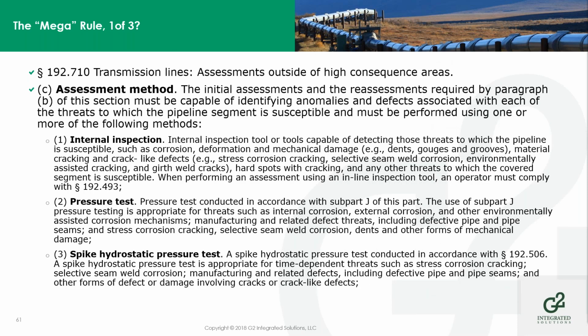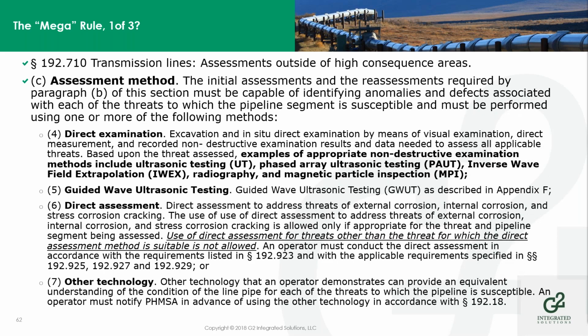The initial assessments and the reassessments required must be capable of identifying anomalies and defects using one or more of the following methods. So we're going to use ILI, we're going to use pressure tests, we're going to use spike hydrostatic pressure test, we're going to do direct examination, guided wave ultrasonic testing, direct assessment. Use of direct assessment for threats other than the threat for which the direct assessment method is suitable is not allowed. So the use of direct assessment has to address the threats of external corrosion, internal corrosion, stress corrosion cracking, or any other technology, again, after notifying PHMSA through 192.18.